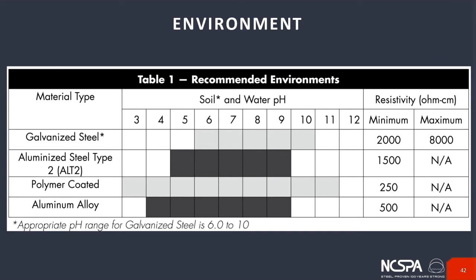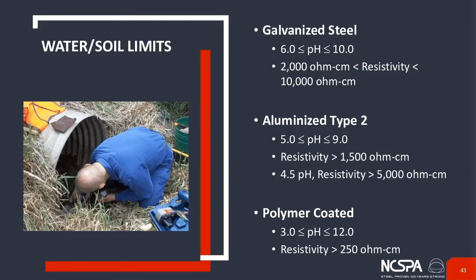So you can see aluminized here from 5 to 9 on the pH and a minimum of 1500. Polymer pretty much covers the spectrum on pH by virtue of its composition, and then resistivity, anything above 250 is fine there. So now we can take this chart and reformat it just a little bit to illustrate those environments in a little bit different way. But again, this is really just to illustrate that this isn't just for the water moving through the pipe, but for the environment that it's installed in as well.